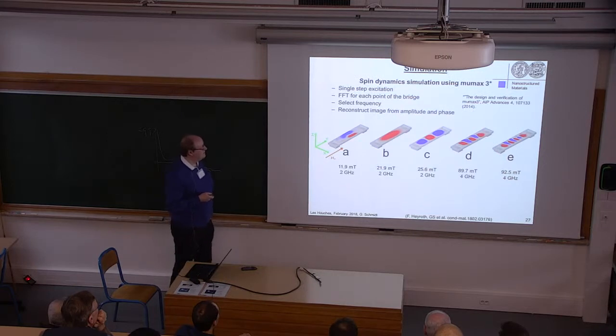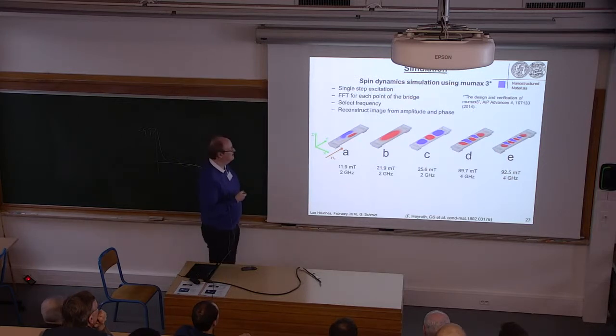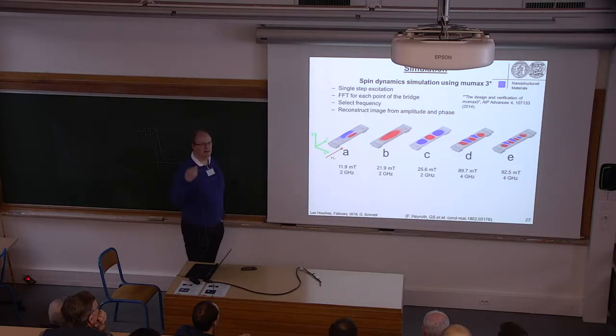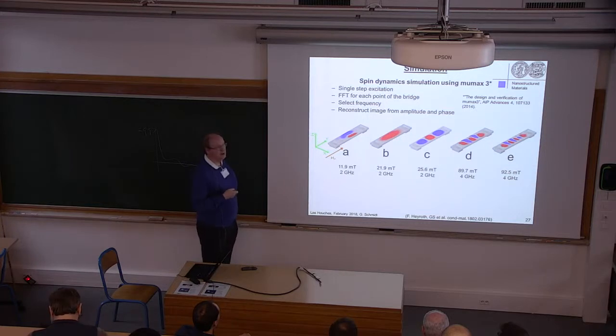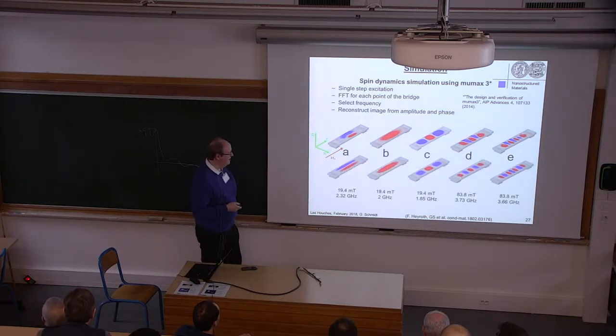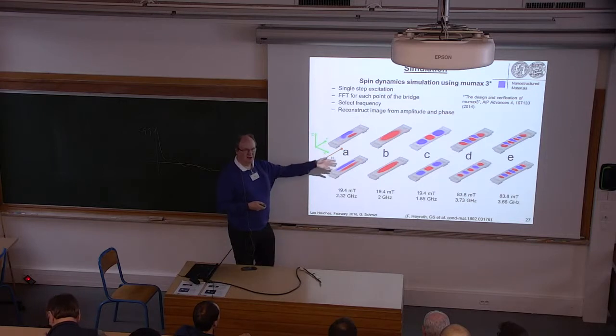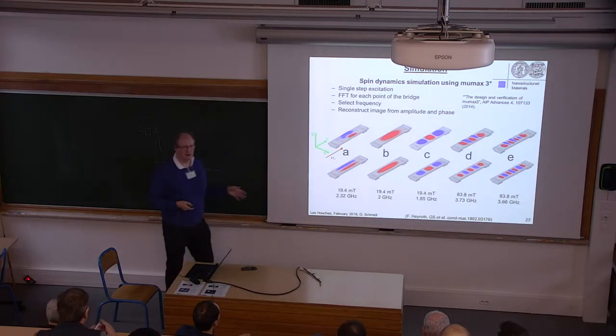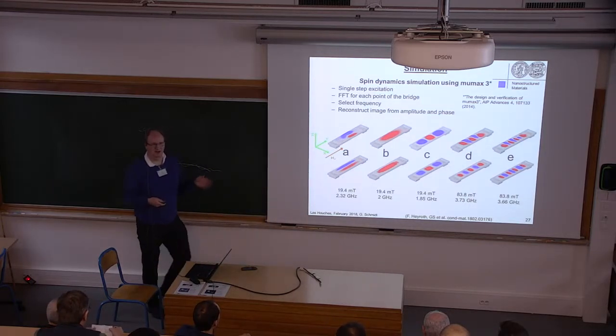And you want to know whether this is correct, what we measure here. So we did some simulation with MuMax3, where we basically did a single step excitation, and we look at the fast Fourier transform, and then we select the frequency. So it's a bit different, because here we vary the magnetic field, and the other one we vary the frequency. But you can see that it fits quite nicely. So they behave exactly as they should.